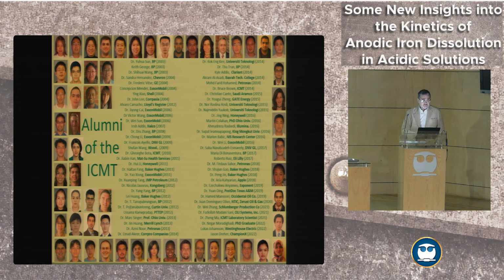Of course, any of these pathways, you add it together, you get that first reaction that I said is too simple and not really true. So this iron dissolution happens according to this story in 4 different pathways, parallel, and each of them has its own kinetics and its own importance. Some depend on chloride concentration, so more salt, less salt, others depend on pH, more hydroxide, less, third depends on, oh my God, complicated.